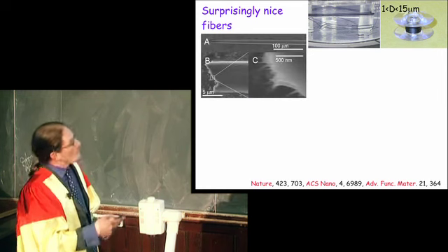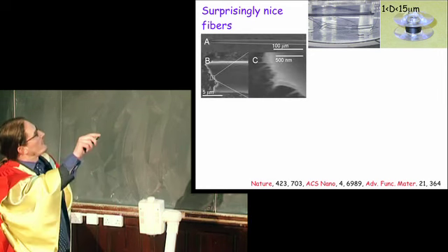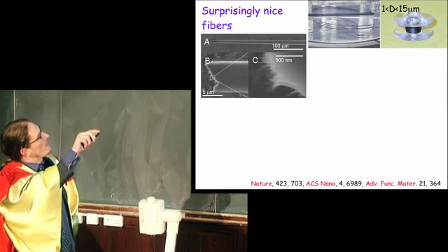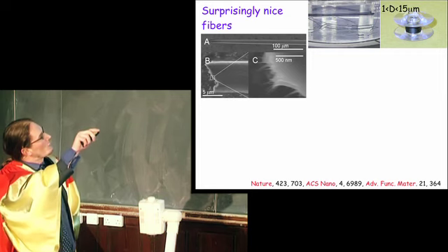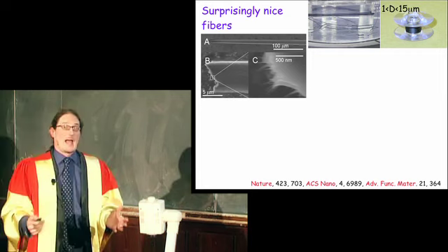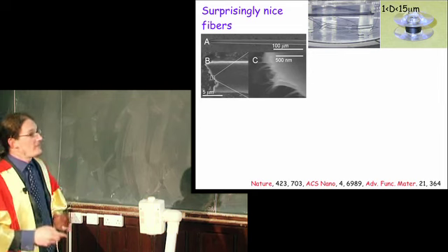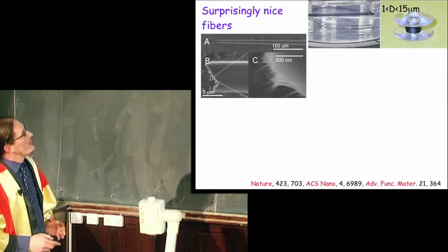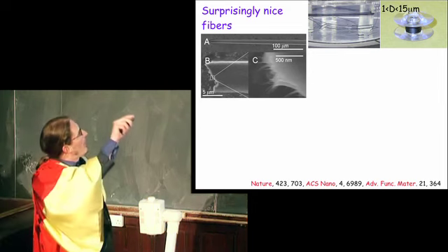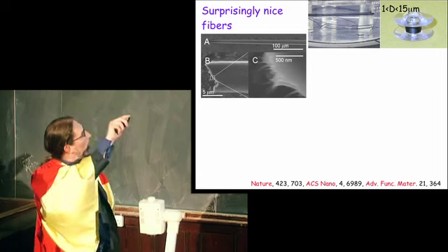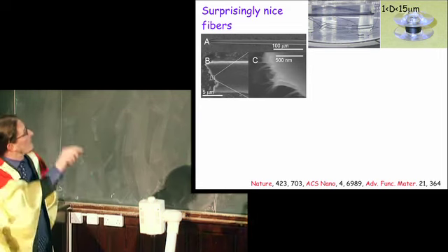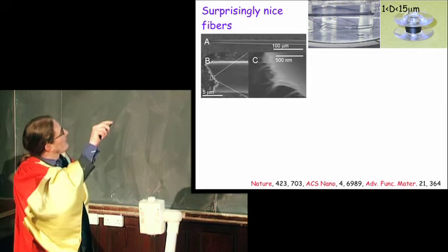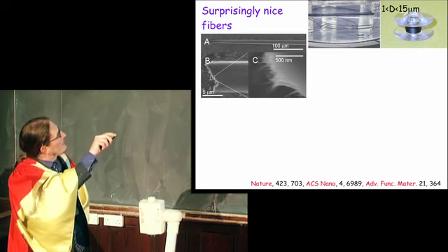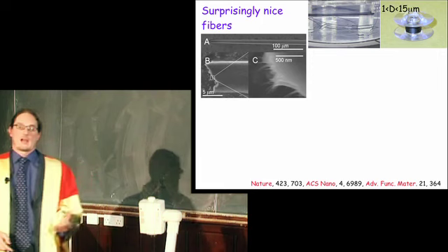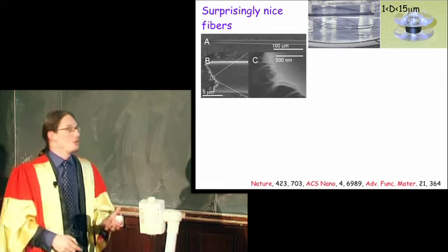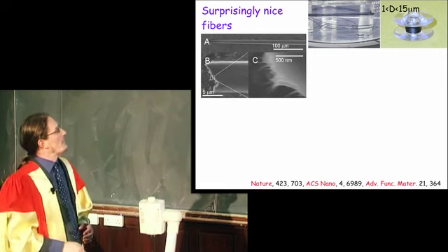When you stop the process, you get these wet fibres collected in the basin. When you dry them off, you get stuff that's just like black thread. Now, is that black thread any good? You can look at it with the electron microscope, and you see that the black thread is actually quite nice, well-defined fibres. If you zoom into the end and look in closer, you can see carbon nanotubes sticking out of the plastic at the end. So that shows we really do have nanotubes in these fibres.